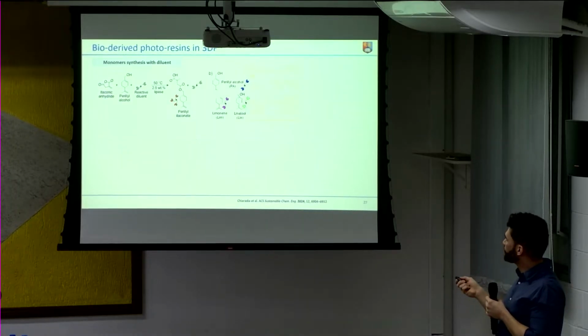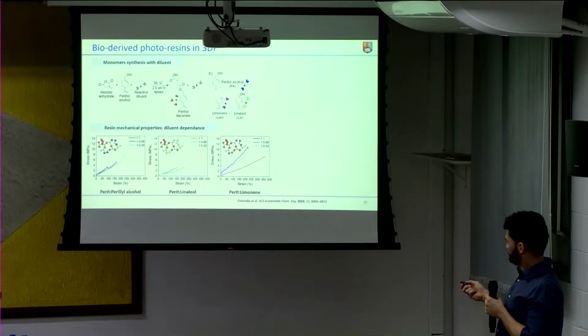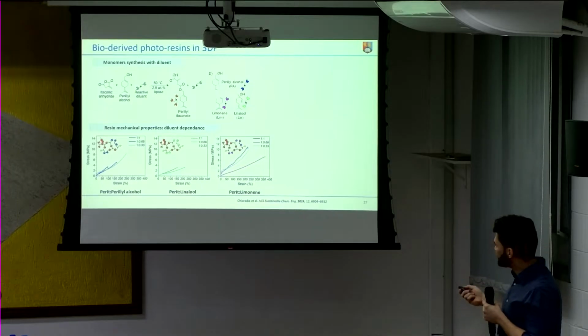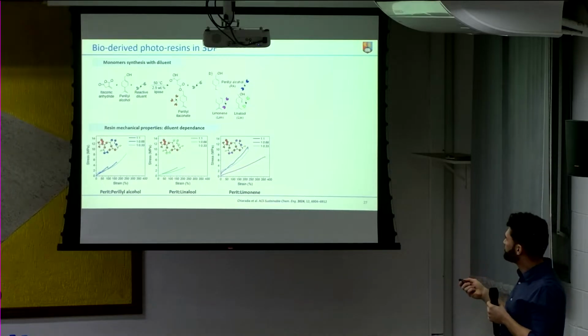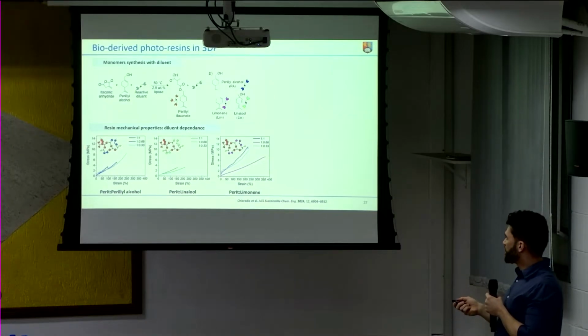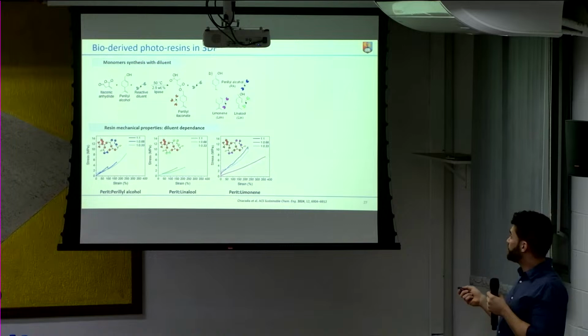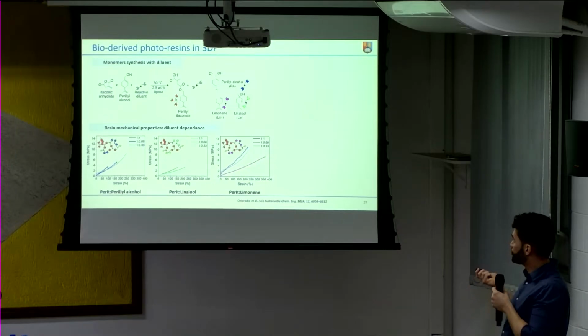So we used other terpenes, perillyl alcohol, limonene, and linalool. Something happened here, it's erased, but still, that's limonene. So we compared the mechanical properties varying according to the diluents. And as we can see here, the resin with limonene as diluent had the best mechanical properties. So that's what we chose to print.